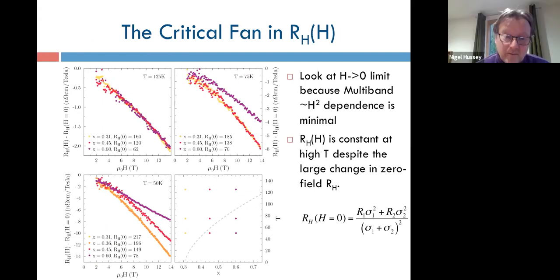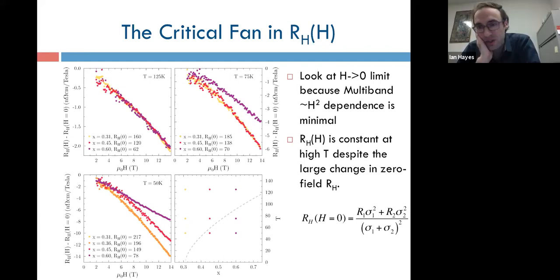it fit. Yeah, but your data suggests a very systematic behavior, almost independent of the model. We've been measuring magnetoresistance and Hall effect, and we really struggle to fit the two side by side in any kind of Boltzmann type picture. I guess what you're saying is it's probably the same here too. Yeah, I think fitting them next to each other is fairly hard.